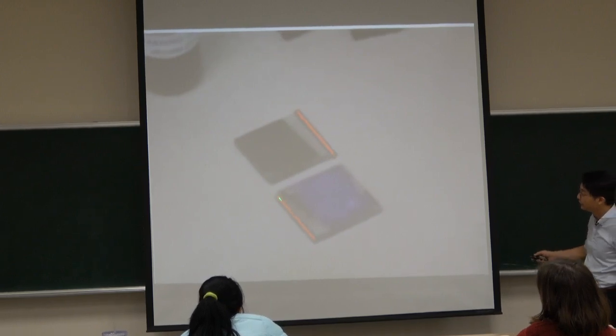Step 2. These two slides, the titanium dioxide coated slide and the carbon coated slide, will be sandwiched together to make a solar cell. Both slides have a 4mm strip on one edge that is clear of any coating. The slides must be assembled so that the coated areas of the slides are touching each other completely. This means the slides will be offset and the 4mm empty strips will be exposed on each side.